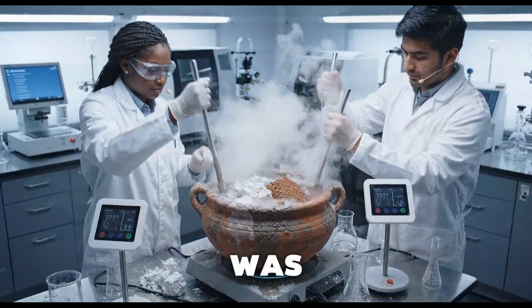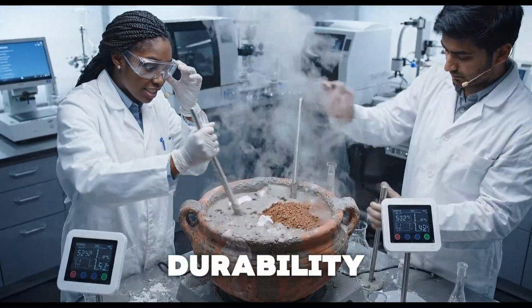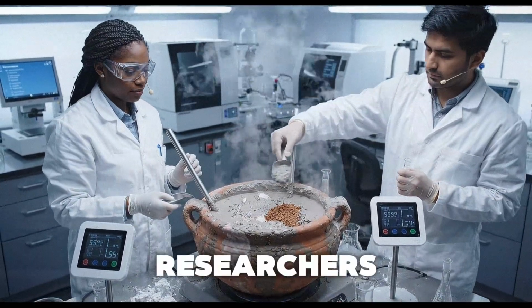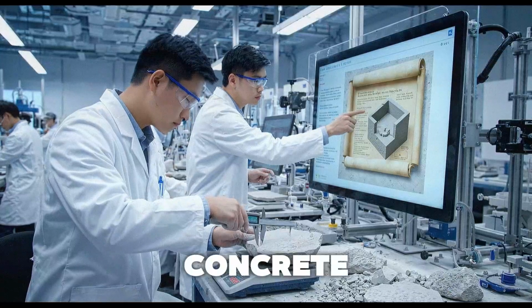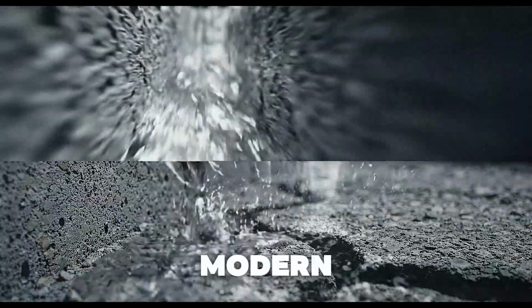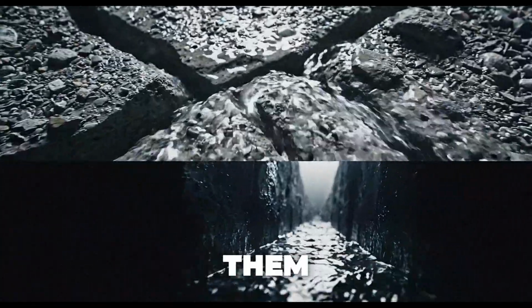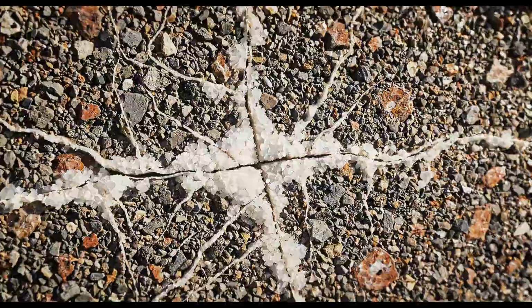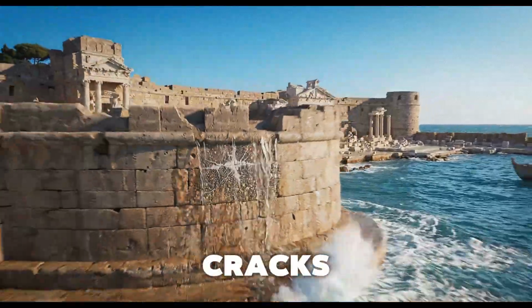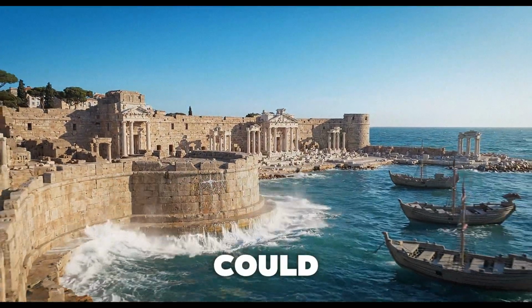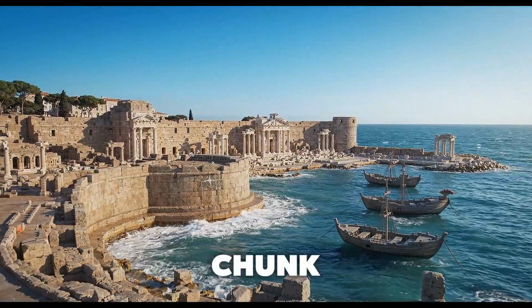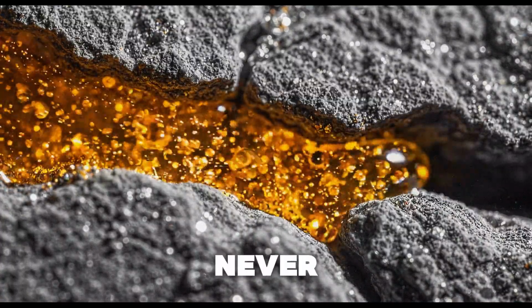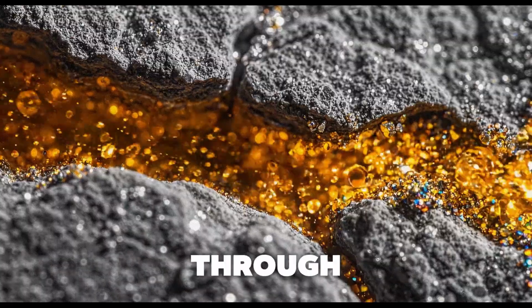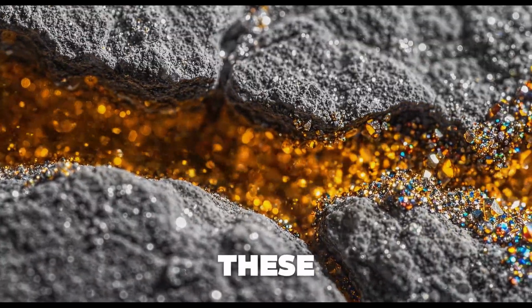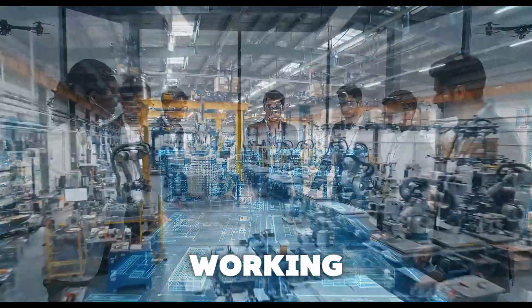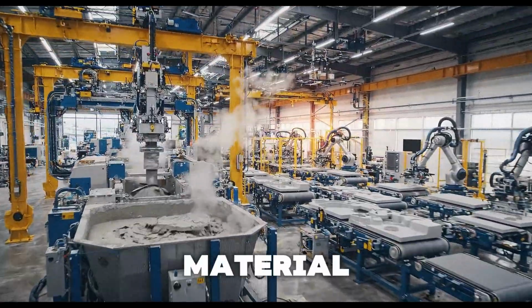To prove that this was indeed the mechanism responsible for the durability of the Roman concrete, researchers produced samples of hot-mixed concrete that incorporated both ancient and modern formulations, deliberately cracked them, and then ran water through the cracks. Sure enough, within 2 weeks, the cracks had completely healed, and the water could no longer flow. An identical chunk of concrete, made without quicklime, never healed, and the water just kept flowing through the sample. As a result of these successful tests, the researchers are working to commercialize this modified cement material.